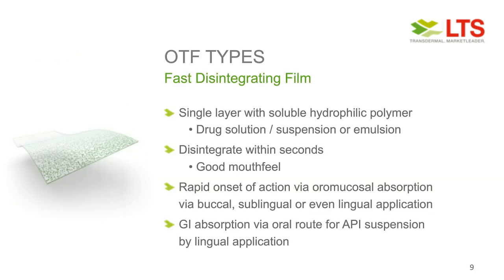So let's start with the fast disintegrating films. These mainly consist of single layers, pretty thin, made out of soluble hydrophilic polymers. And the API drugs are either dissolved in these films or suspended or in an emulsified inner phase. These films disintegrate within seconds. We try to achieve this in less than 10 seconds to have really a fast onset of action. And very important over the last years is the good mouthfeel. So when the oral thin films were launched, a lot of examples also hit the market where the mouthfeel was not well tolerated by the patients. And this is a topic which I would like to talk about later on in this webinar. We focus on this in the last years.